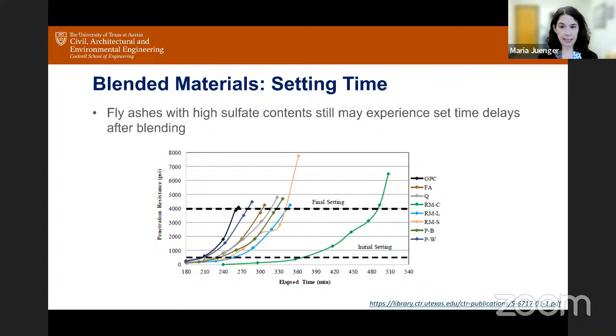If you blend that class C fly ash with a natural Pozzolan or with a class F fly ash to reduce its calcium content, you blend it to try to meet a class F specification. So you're reducing the calcium content of that class C fly ash just to be able to use it. It still won't protect you against sulfate attack because that C3A is still in there. Even though there's less of it, it is there.